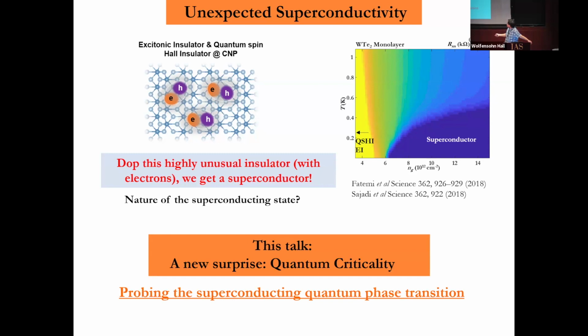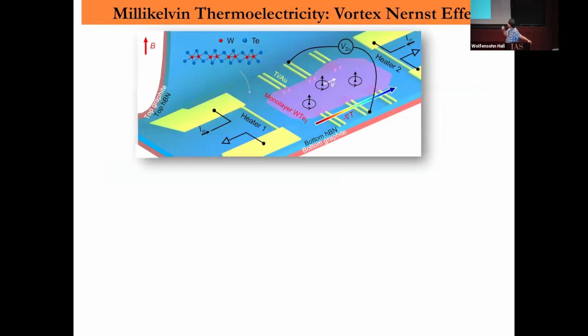So the key here is to probe the quantum phase transition by looking at quantum fluctuations, and I will explain that. The way to probe it, you will see soon why this experiment will help. The way to probe quantum fluctuations in this case is to measure the Nernst effect, which is a thermoelectric effect: you apply a temperature gradient, and you observe a voltage drop in the transverse direction.